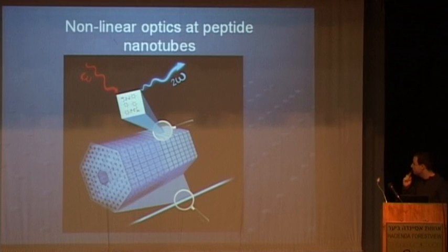This is the model of the peptide nanotubes and a little bit of what we think occurs over there. We've got the peptide nanotubes. They have a hexagonal symmetry, and they also look hexagonal. They have multiple hollows on the order of 1 nanometer inside, which go along all the peptide nanotubes. I believe that the nanotubes are created from nanocrystalline regions on the order of 1.2, 1.3 nanometers, which are composed of 2 phenylalanine residues, as we can see here on the blue square. And each crystal can give second harmonic generation, as we can see here on the wavelengths.